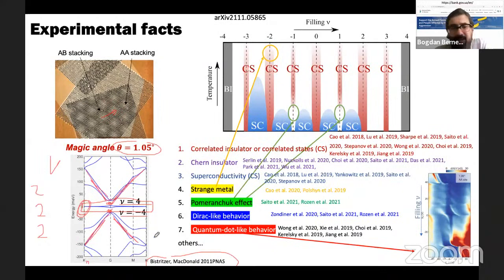And normally, as you gate tune the system through -4, -3, -2, all the way up to 4 electrons, you should see a metal from -4, it's an insulator, to 4 electrons. However, the phase diagram, experimentally seen, looks something like this. And it's a bonanza of many body states. So for example, at every integer filling, instead of seeing a metal, you see an insulator.